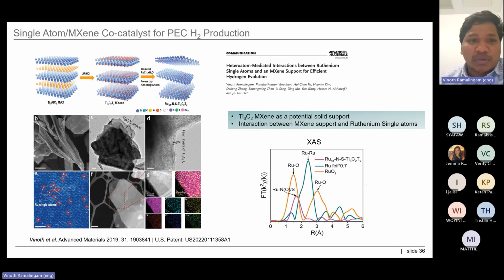So this is one of my previous works back at KAUST, where I developed ruthenium single atom incorporated MXene as a co-catalyst material for photoelectrochemical hydrogen production reaction. I tried a wide range of single atoms, but ruthenium was the best one, which gave us better performance. And we thoroughly characterized our materials using various techniques. Here you can see the dark field scanning transmission electron microscopy image, where you can see the bright dots. It indicates the presence of the ruthenium single atom as well as clusters. I forgot to put the scale, which is